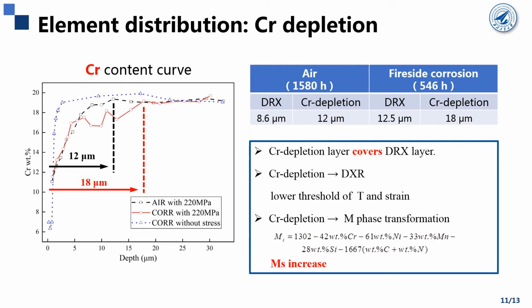To find out why this happens, we measure the chromium concentration change as a function of the depth to the surface. And then we can see that chromium is significantly depleted in the surface layer. And the thickness of the chromium depletion layer in fireside corrosion is apparently larger than that in air condition.